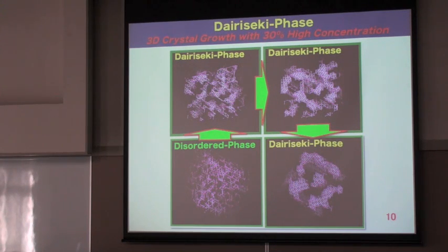If the exchange interaction is very short range, for example in ferromagnetic semiconductors, in this case TC is very low because you have a very small percolation path. But if you can organize spinodal decomposition, you have a complete percolation path on your whole crystal. You can realize a very high TC. I will discuss that later.